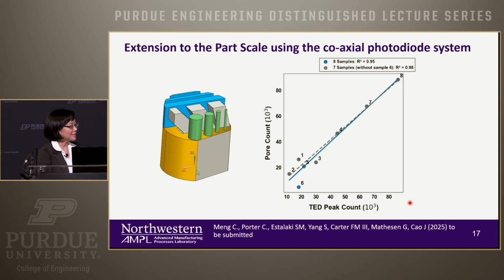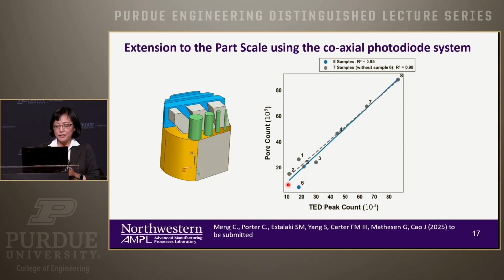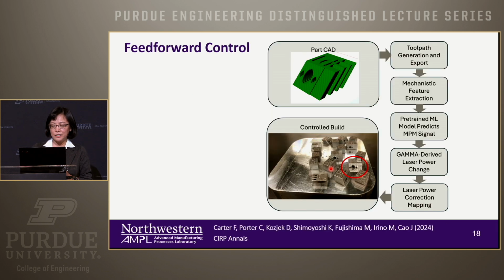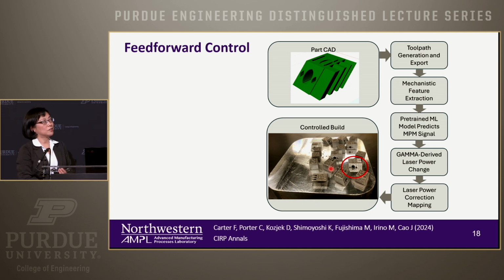So we count the TED peak versus after, as I mentioned to you, with the 8 different sets of the parameter, they have the pore count. And you can see that it's a really great correlation. The one that's an outlier right here is because the process parameter of this one is lack of fusion, not due to the keyhole.